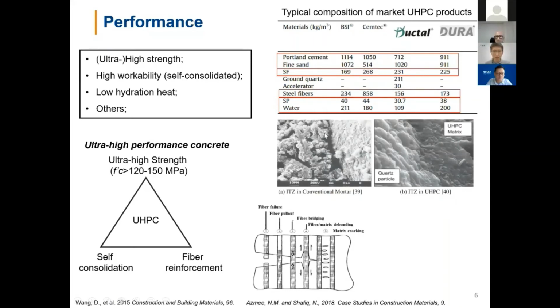With this recipe, we're able to generate a matrix that is very dense and very strong. If you look at the microscale image of conventional concrete, the interfacial region between the paste and the aggregate is usually very weak and porous, and that's the weak zone. That's the place where concrete will fail first. However, in the ultra high performance concrete, this weak interfacial zone is now completely fixed. It's very dense and strong. The addition of the fiber further enhances the strength of our concrete and also enhances the ductility of the concrete.